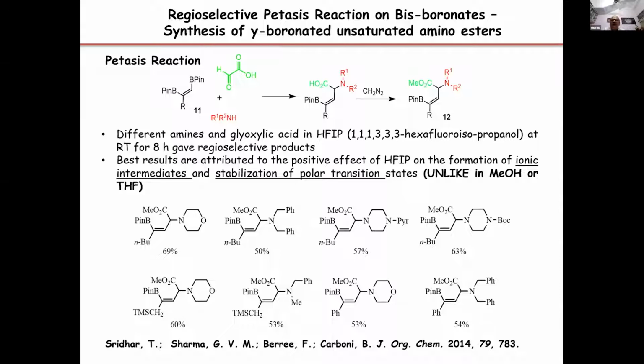Here we have used hexafluoroisopropanol as a solvent in this reaction. Unlike the reported literature solvents, methanol and THF, here we observed the formation of better results, wherein we assume HFIP is supporting the formation of ionic intermediates and the stabilization of the polar transition states.